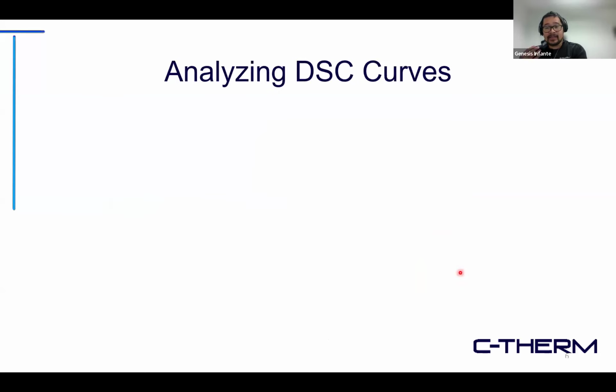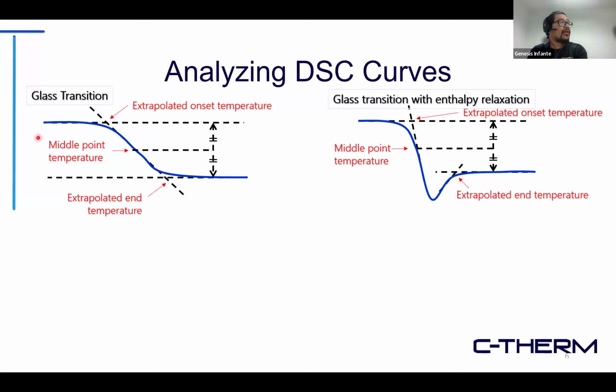In terms of analyzing, in a more quantitative sense, what we can gather from the DSC curves, we can get different information like the melting temperature and the onset. For example, if you look at the glass transition right here, you can see that there is a baseline shift. Another type of glass transition typical of DSCs for polymer materials is a glass transition with an enthalpy relaxation. So you can see a big dip in the energy and a baseline stabilization right here.